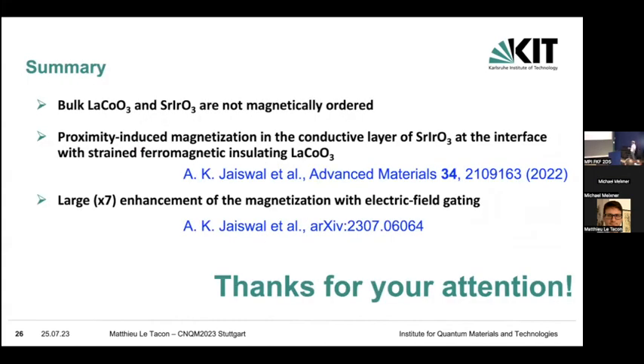Good. So in summary, we found this interesting magnetism at the interface between two materials which in the bulk state are not magnetically ordered. So it's really interesting new physics going on from the combined effect of strain and confinement at an interface of these materials. And there's a proximity-induced magnetization in the conductive layer of strontium iridate at the interface with ferromagnetic insulating lanthanum cobaltate that we can control by electric field gating. And I thank you for your attention.